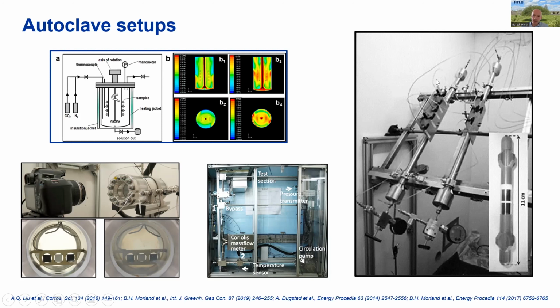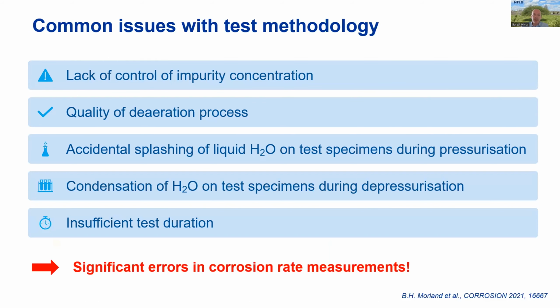And then there are kind of intermediate setups where we have a rocking or a rotating autoclave. Again, this one is at IFE in Norway. And these can simulate flow by every time the autoclave is rocked, the specimens are on a kind of sliding mechanism. So gravity then shoots them up and down and simulates the flow past the specimen. However, all of these setups have their pros and cons, and we need to use a combination of all of them to fully understand how to measure corrosion rate most accurately and make it as representative as possible of service conditions. So the issues that have been identified with common test methodologies are as follows.